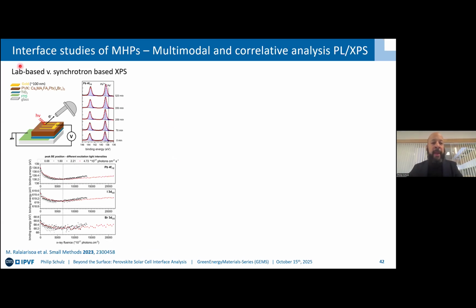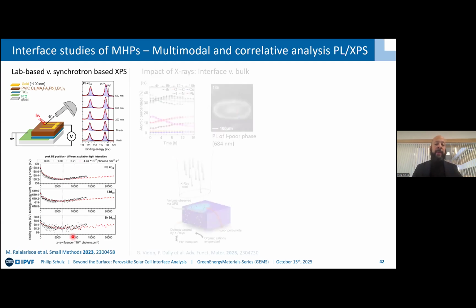So, for instance, comparing lab-based with synchrotron-based XPS, you can also see the degradation. It's really that the dose makes the poison. So you need to go down to a low X-ray dose. You need to work with conformal, homogeneous samples, where you can evaluate multiple spots and average afterwards in order to get to reliable data.